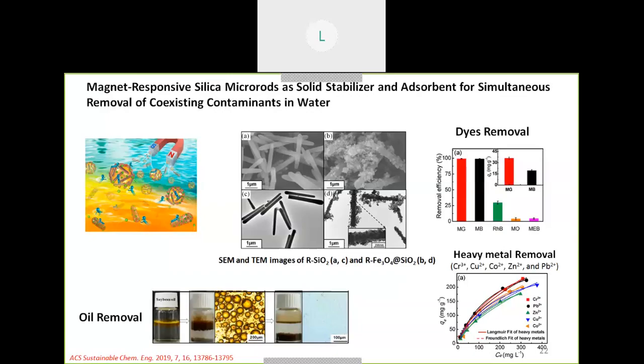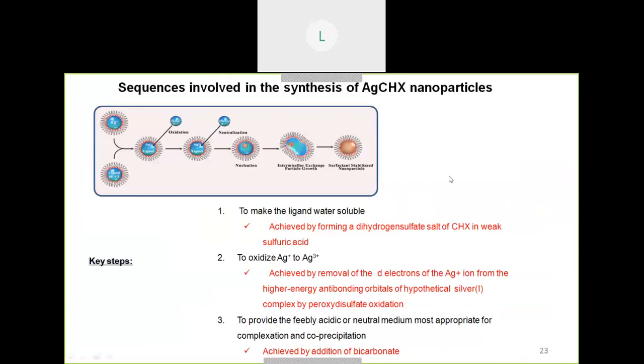And coming to the disinfection processes, disinfection agents, this was done by my supervisor. He synthesized very good antibacterial agents by application of the CHX chlorohexidine and the silver precursors. So what he did, he oxidized the silver into the higher state. As the Ag3+ state is very unstable in the environment, we have to encapsulate it with something so that this state can be maintained. And this state has the highest antibacterial activity amongst the other oxidation states of silver.